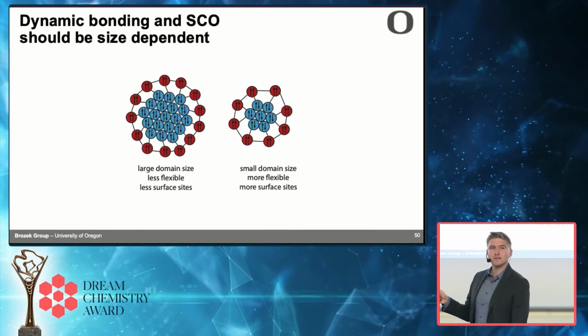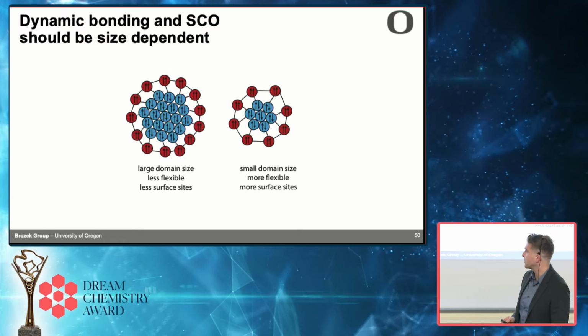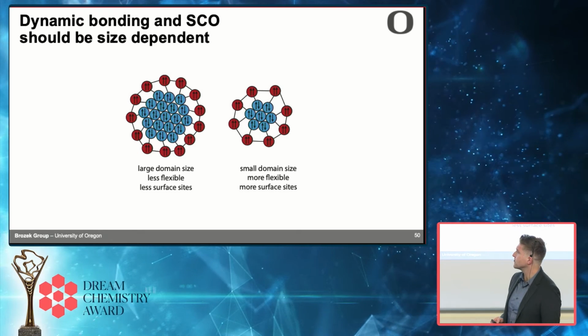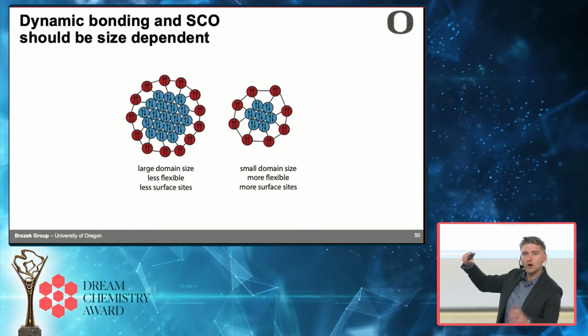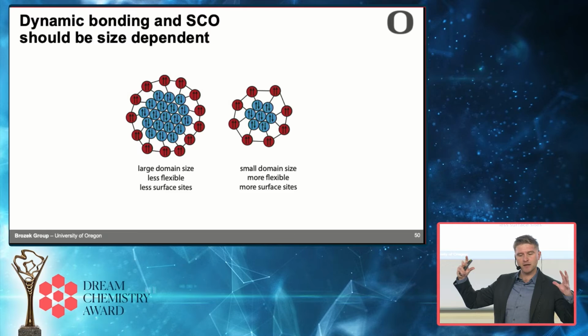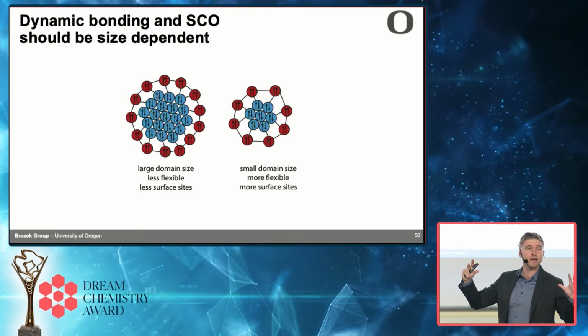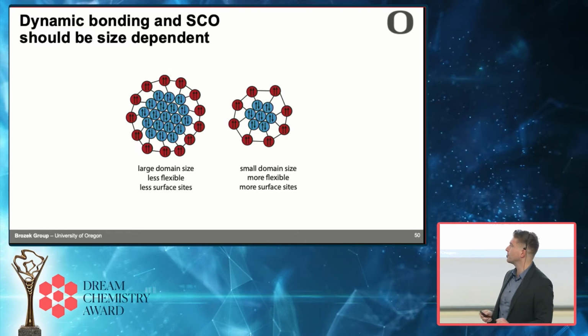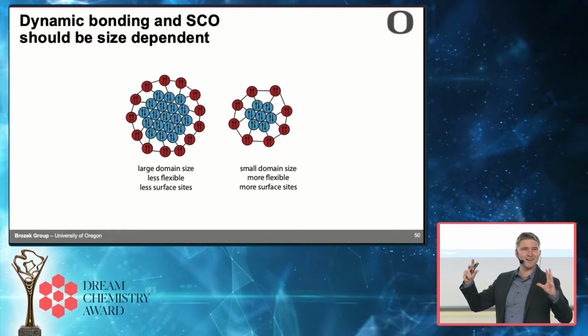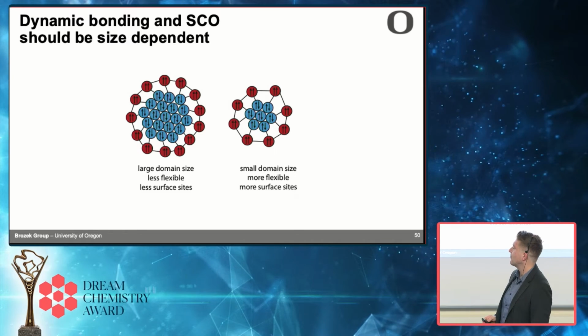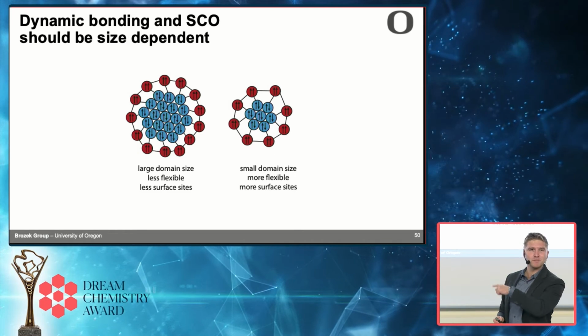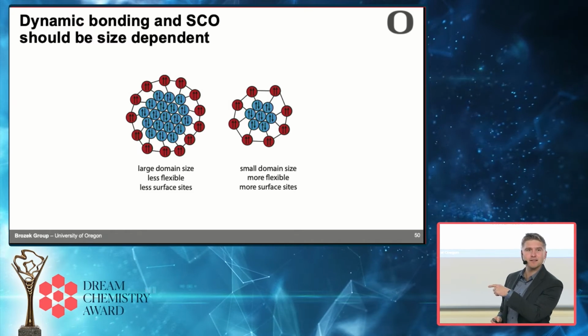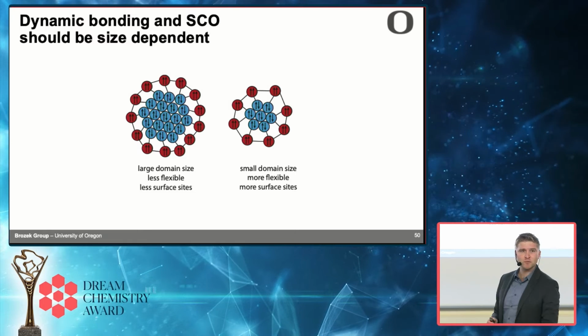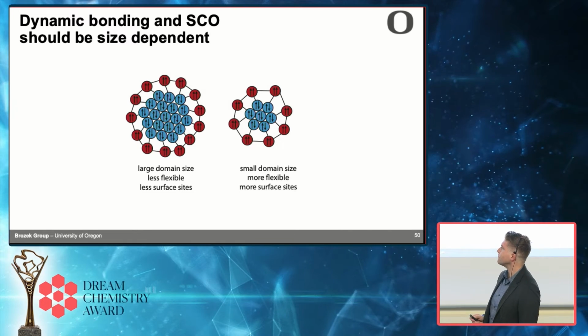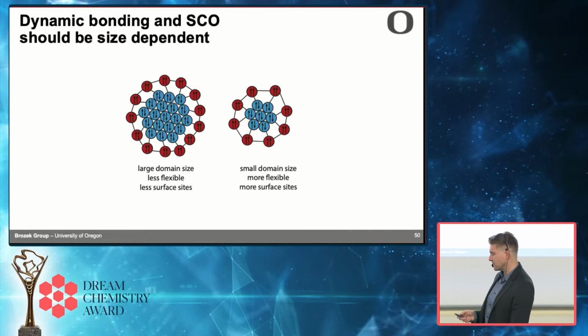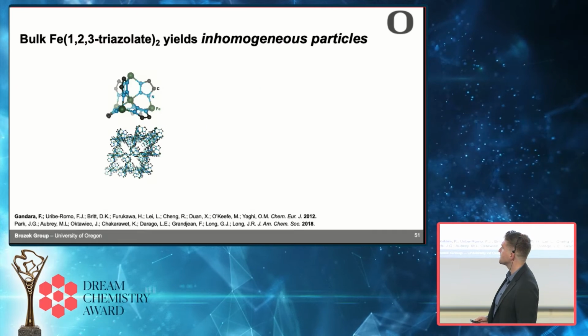This behavior should be size dependent, okay? So spin crossover is thought to start at the outside of the particle, and that's because that's the most flexible place in a material, the most accommodating of becoming high spin. And so we thought if we could make this material of different sizes, that spin crossover should become size dependent. So we needed to be able to make this material of different particle sizes.